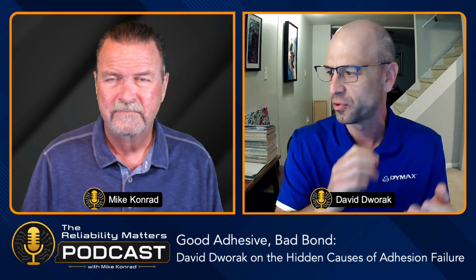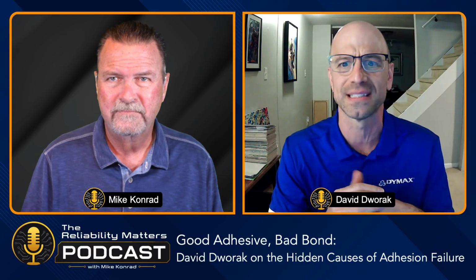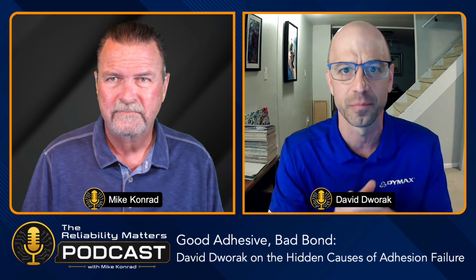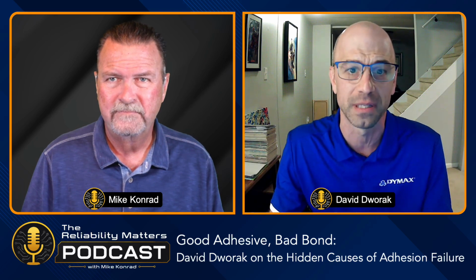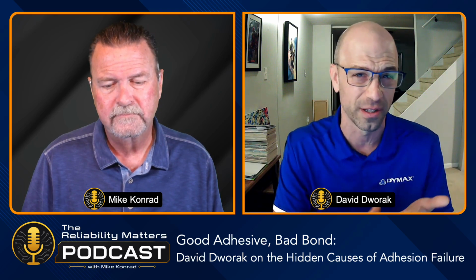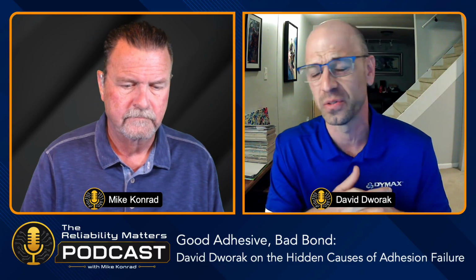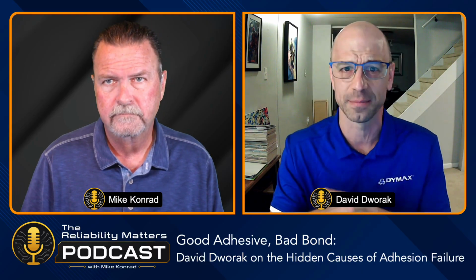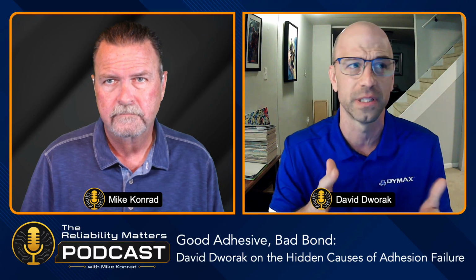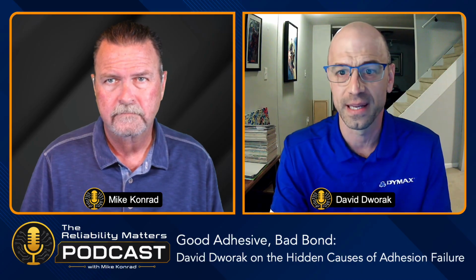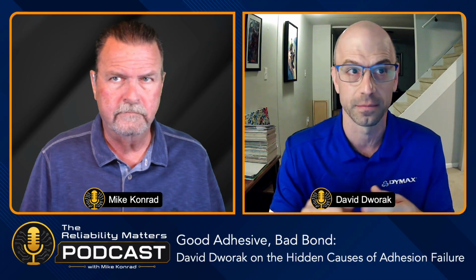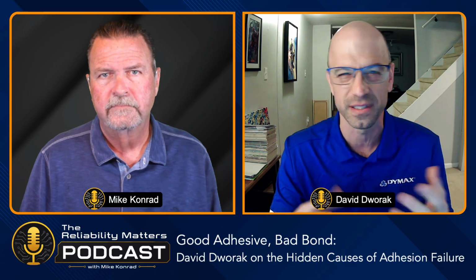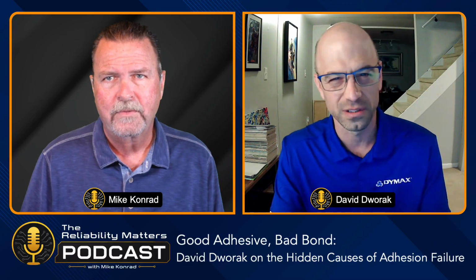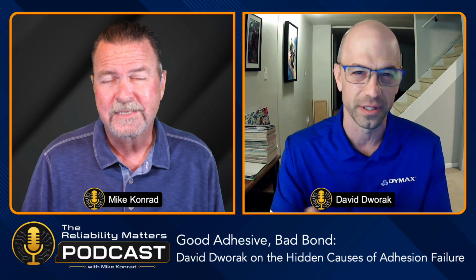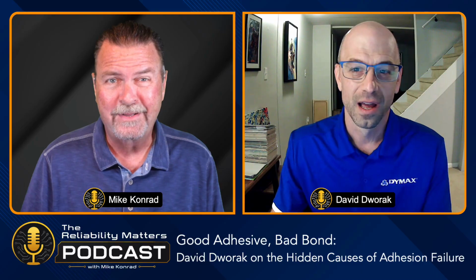It can be put into just about any processing line and can be used on pretty much all metals and plastics without you having to worry about it marring the surface or causing any issues like that. So in that aspect, it's very nice. But one thing you need to consider with IPA is its purity. There's 70, 80, 90% diluted with water. Water is not always clean. There could be impurities there. 70% is rubbing alcohol. That's what a lot of people use.